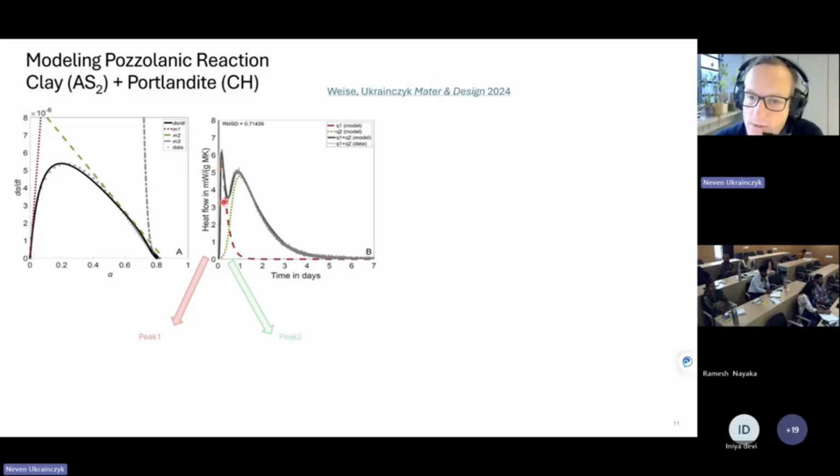And what she found out, we also measured very early reactions. We developed a new methodology for how you can also measure early reactions in heat calorimetry. Usually the R3 test is at 40 degrees, and you need to mix it outside and then put it inside. But we made a method so you could also measure it from very early. And she found basically that within half a day there is a first reaction and then there is a second reaction.